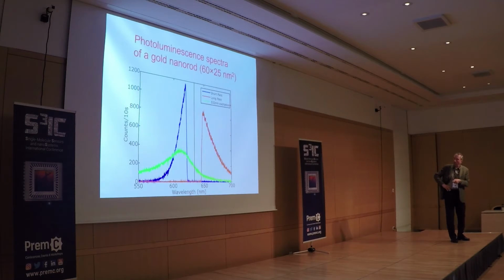And what you see is there is, of course, red-shifted luminescence. That's the Stokes shifted luminescence. That's the one you expect. But in addition, you see that there is anti-Stokes luminescence on the blue side. And why is that? Of course, there is always anti-Stokes, but the anti-Stokes luminescence is made visible here and is actually stronger than the Stokes luminescence because of plasmon enhancement.